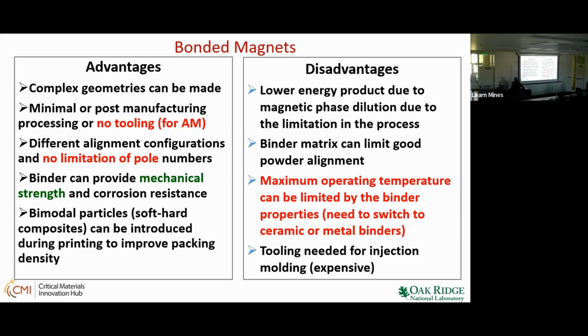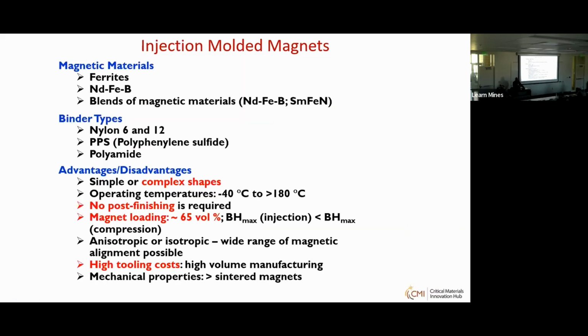And the operating temperature again depends on the polymer. Sometimes somebody comes to me and says, I need a magnet that can operate at 500 degrees Celsius. You can do it. You can use a ceramic binder and some samarium cobalt, or you can use a sintered magnet. So those are possible. And the tooling can be very expensive.